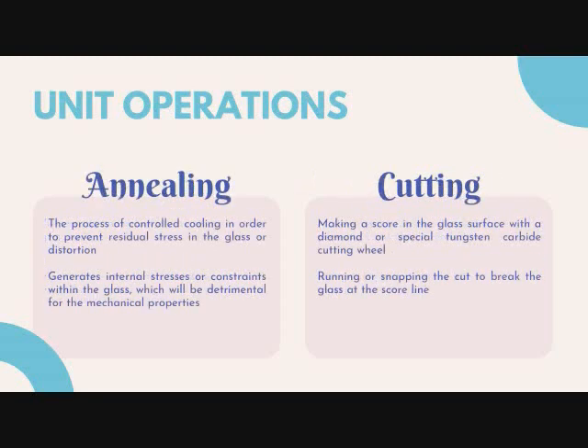So annealing is the process of controlled cooling in order to prevent residual stress in the glass or prevent distortion. Rapid cooling of the melt is necessary to obtain a glass product rather than it be crystallized. This rapid cooling will generate internal stresses or constraints within the glass, which will be detrimental for the mechanical properties. These constraints can be relaxed by careful thermal treatment called annealing by lowering the temperature of the rigid glass ribbon that came out from the float bath from 600 degrees Celsius to 250 degrees Celsius by passing through a cooling tunnel called lehr. Good annealing is essential to produce good commercial glasses, as it assures durability.